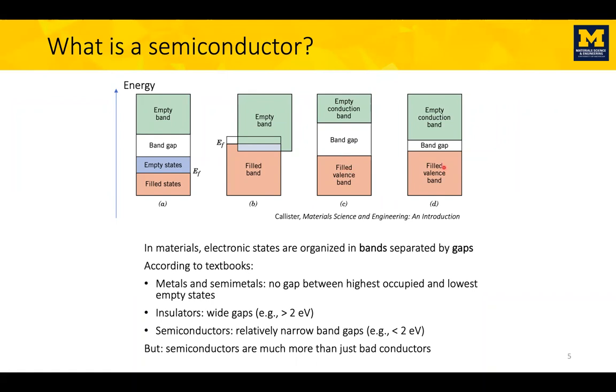In contrast, semiconductors also have a gap, but the gap tends to be narrower. So for example, the band gap of silica is around 8 or 9 eV. Silica means silicon dioxide, the insulator in our circuit, but silicon itself has a band gap around 1 eV. And because the gap is narrower, it's easier to conduct.